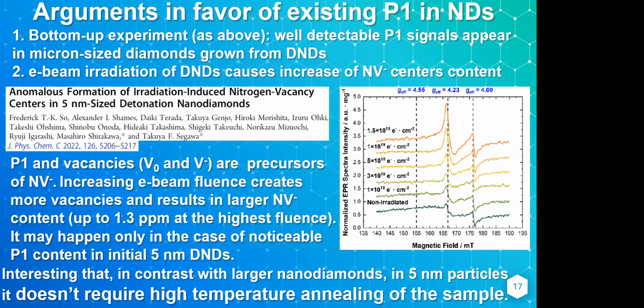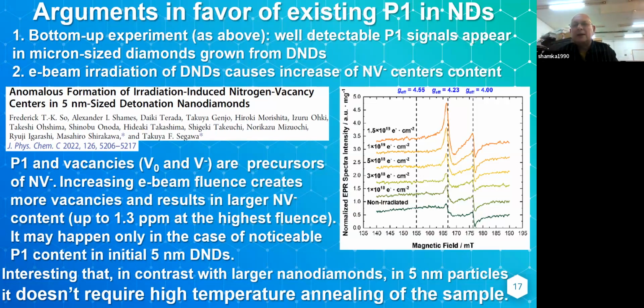Like you see a suppression in the signal intensity in EPR of that central line, which you can attribute to these surface dangling bonds that are in the subsurface, near subsurface, like you were saying. Yeah, it sounds very interesting.